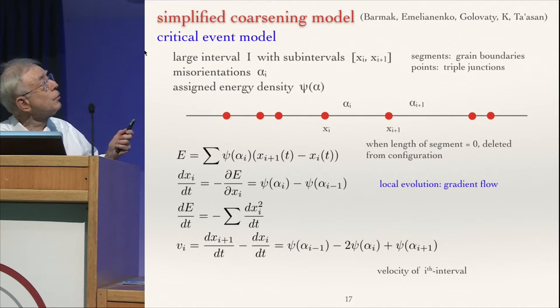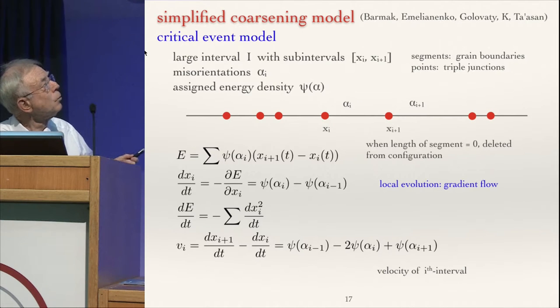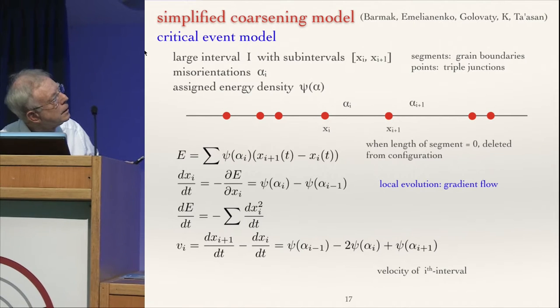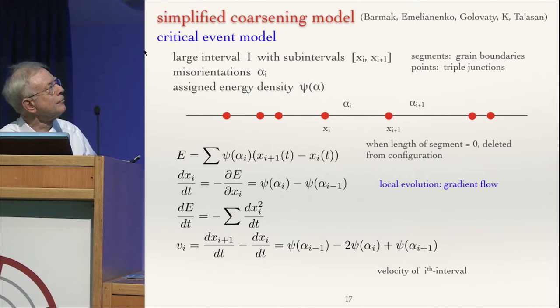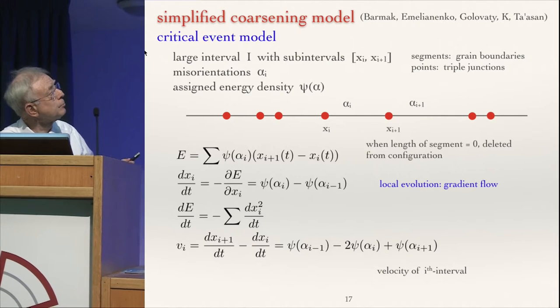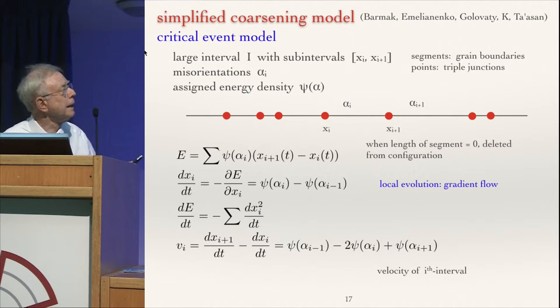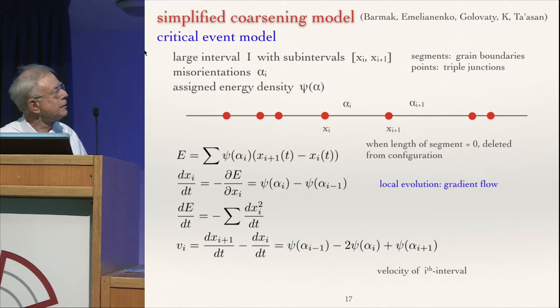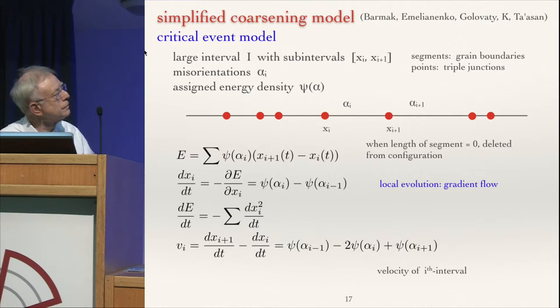So I show you what this simplified coarsening model is. We had used it for other purposes with Barmak, Emelianenko, and Dmitry Golovaty, who is a former student. You just take an interval, and you prescribe an energy and put parameters on each of the subintervals separated by these red dots. You write down an energy, which is psi of alpha i times the length of the interval, and you make a gradient flow: dxi/dt is minus dE/dxi. That's this difference. Then dE/dt is minus the sum of (dxi/dt) squared. So this is our local evolution gradient flow. And when the length of a segment disappears, you take it out.